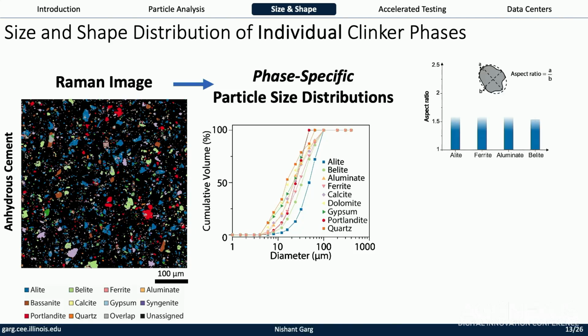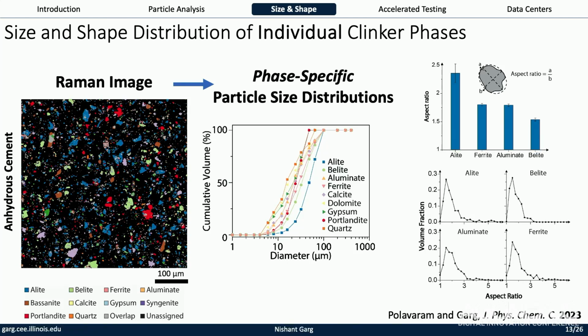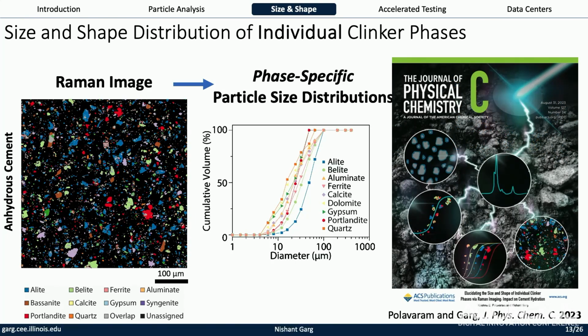And then we can get all sorts of other metrics, such as size and shape of these individual phases, which turn out to match, right? Your belite tends to be round, and we see that. And this work came out on the cover of JPCC, so we were very proud of that. My student went and did some nice graphics for this.